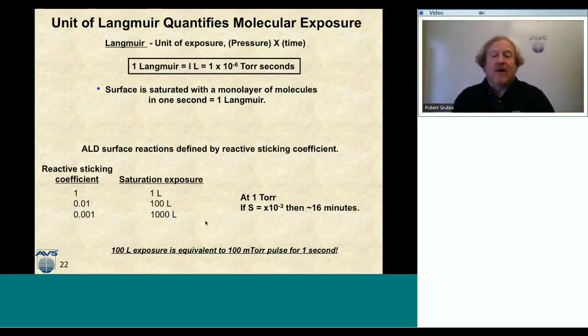All right, so at 1 torr with a sticking coefficient of 1, it's going to take about 1 second of time before I have that surface covered in a monolayer of molecules, with a sticking coefficient that's very small. Just to calibrate you folks on the other end about the Langmuir, a 100 Langmuir exposure is equivalent to a 100 millitorr pulse for about a second.